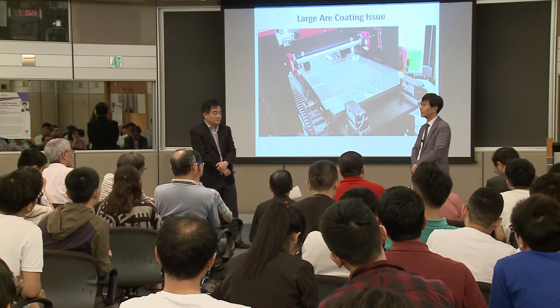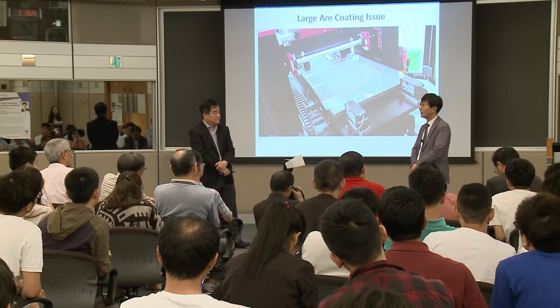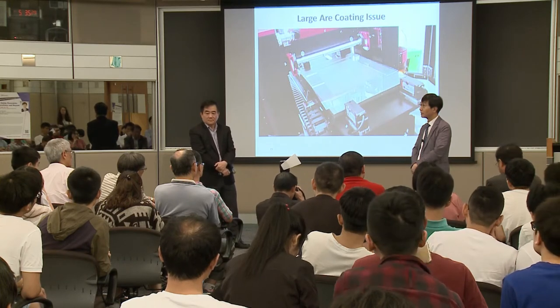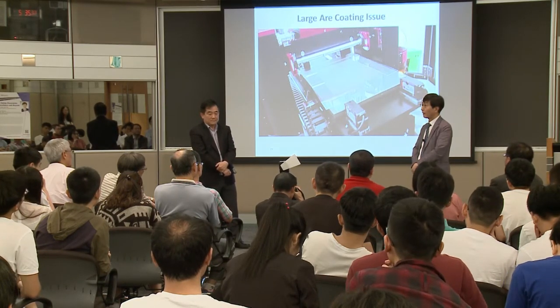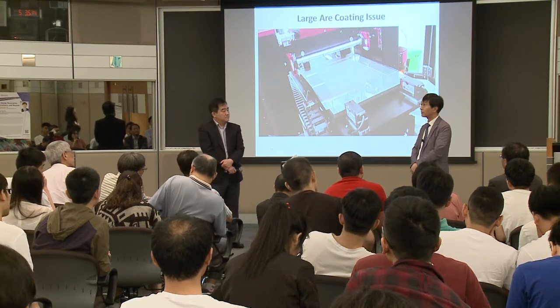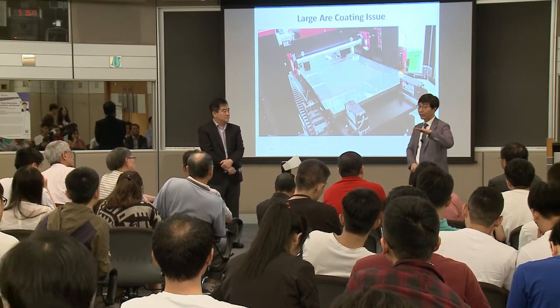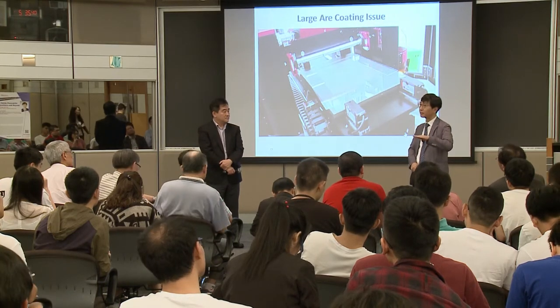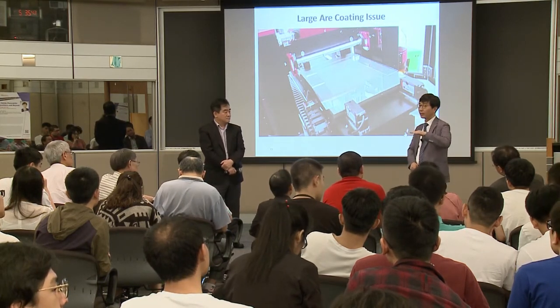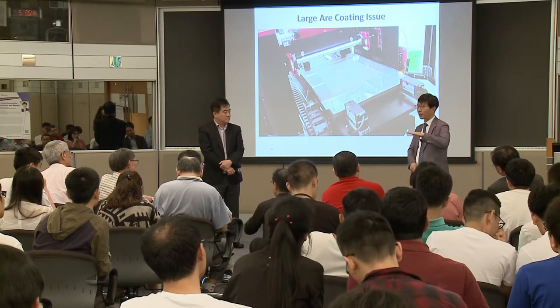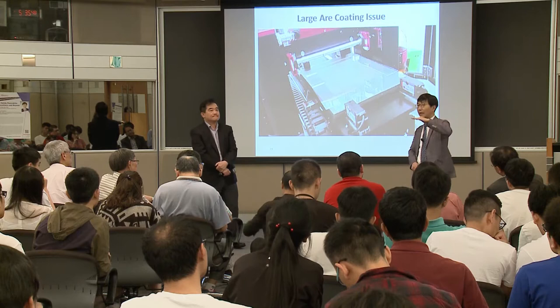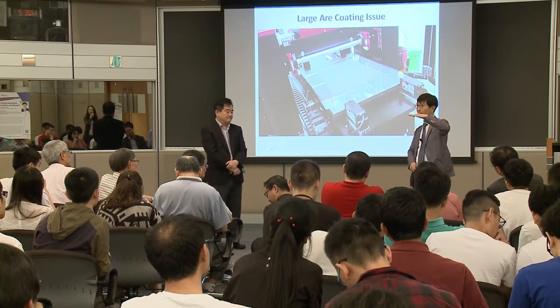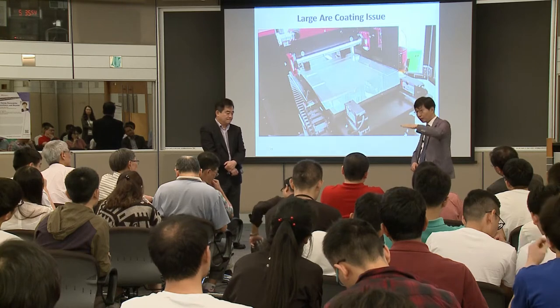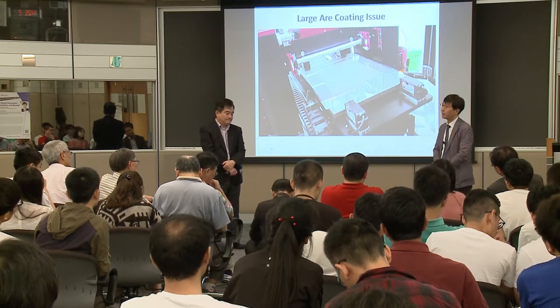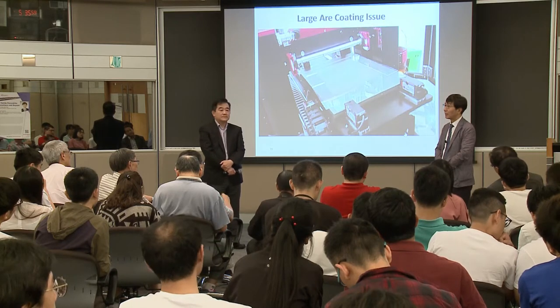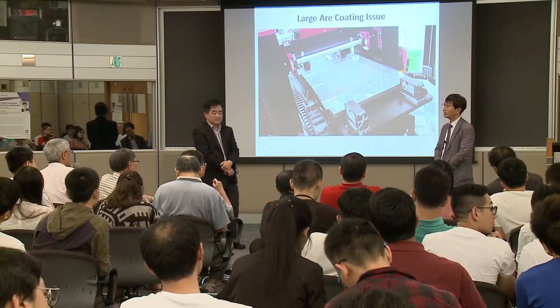Okay, the spiro compound looks glassy, so it loses its conductivity. Frankly speaking, this spiro compound itself is a little bit stable at 85 degrees C, and even stable on top of the perovskite. But in the whole device, using the gold electrode or the silver electrode, with this full structure, the spiro compound undergoes a glassy state.